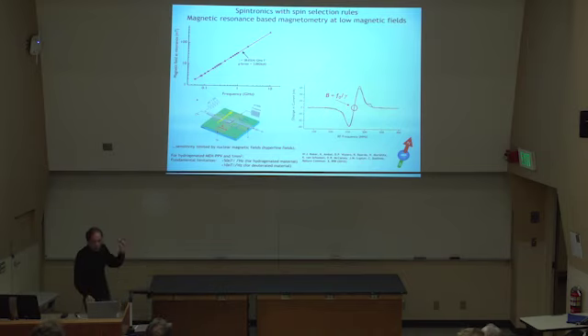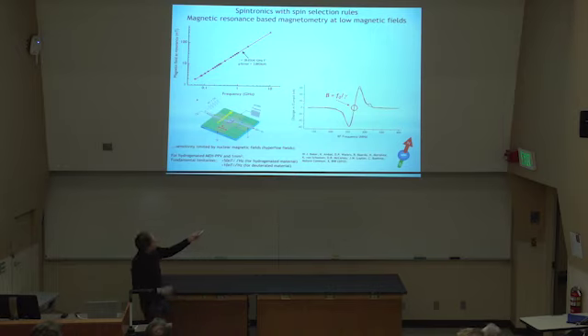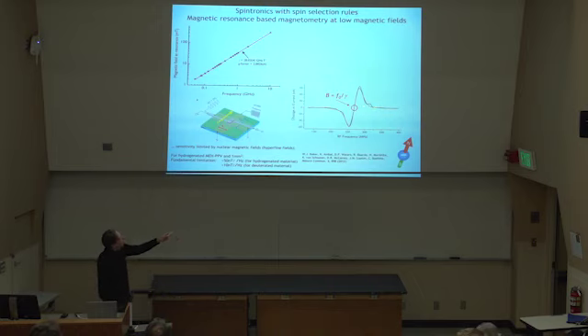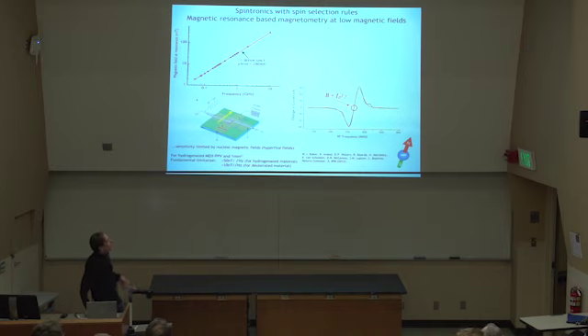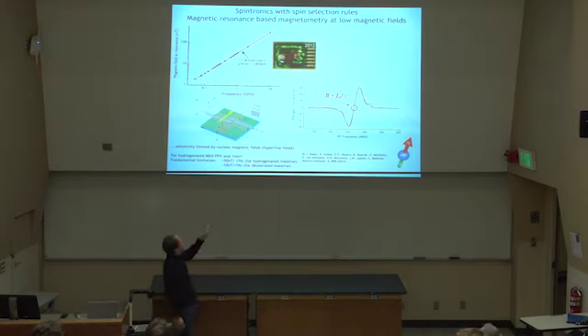So we've been pursuing this for a few years. Started out with a patent. What you do is you sweep your frequency and see where you get your current change signal. This is a derivative signal detected due to the amplitude modulation of your excitation. And then if you see the zero crossing here, if you know at what frequencies the zero crossing happens, you know what magnetic field you have, because you have a magnetometer whose standard is the gyromagnetic ratio of essentially vacuum electrons, if they're sufficiently weakly spin-orbit coupled, and that is basically an electronic device that measures calibration-free your absolute magnetic field. So this is how we started really in a primitive way, a PCB that was like 1 inch by 1.5 inch in size. And then we put, you can hardly see it, this orange area is a glass slab that we flipped on top of it that has the polymer device on it.